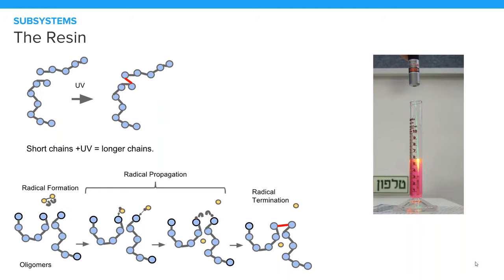You can't melt it down again and use it. Once it's cured, it's done. That's opposed to thermoplastics like PLA or ABS, which are not chemically changed on bonding, and those can actually get melted down and reused. One of the other big differences is that SLA resins are better for making watertight parts, because the entire component, once it comes out of the machine, is chemically bonded and unified. So there's no discrete layering, essentially. Whereas in an FDM machine, each layer is mechanically bonded through heat, but it's not a single part. They're still discrete mechanical layers.